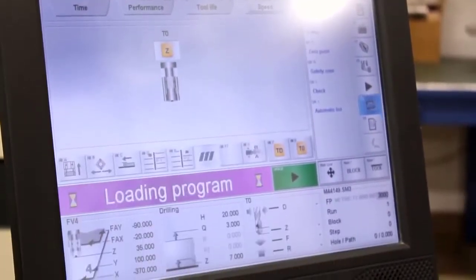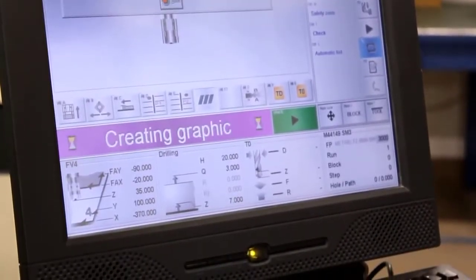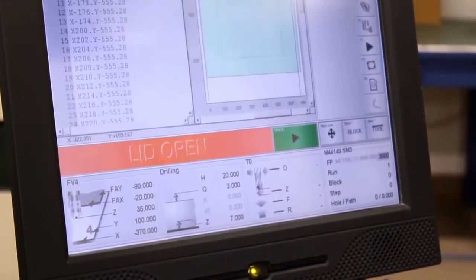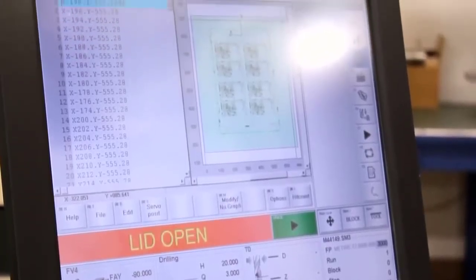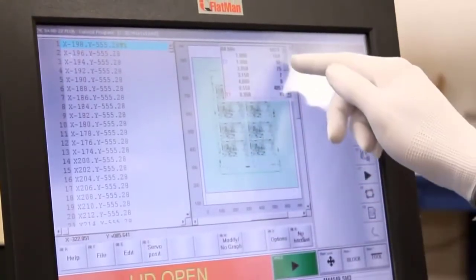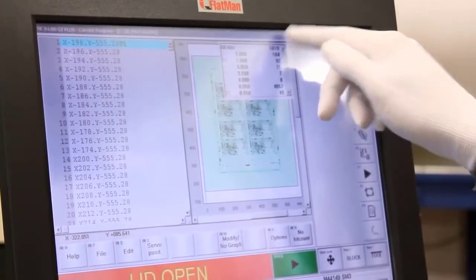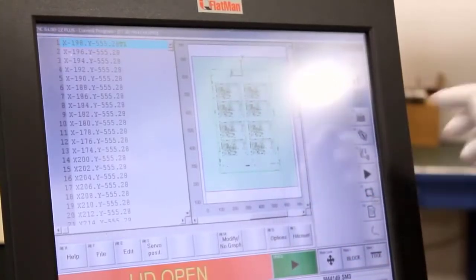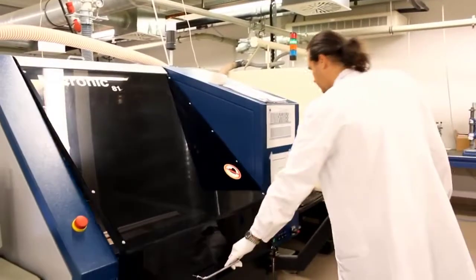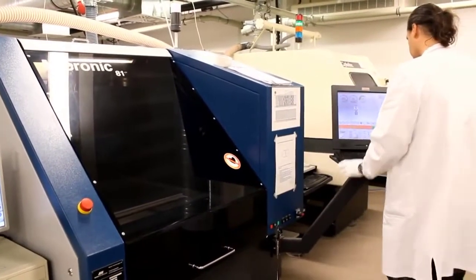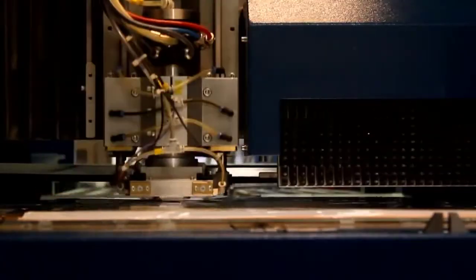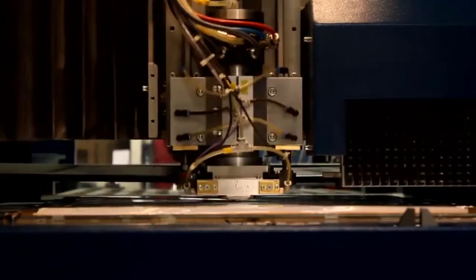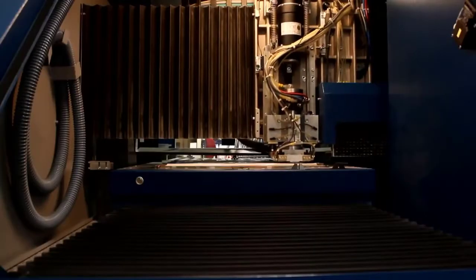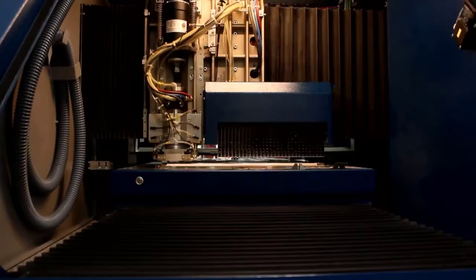Our drills use air-driven spindles which can rotate up to 150,000 revolutions per minute. High-speed drilling ensures clean hole walls to provide a secure base for good plating on the hole walls. Drilling is a slow process as each hole must be drilled individually. So depending on the drill size, we drill a stack of 1 to 3 PCB panels together. We can drill holes down to 100 microns in diameter. To give you an idea of the size, the diameter of a human hair is about 150 microns.